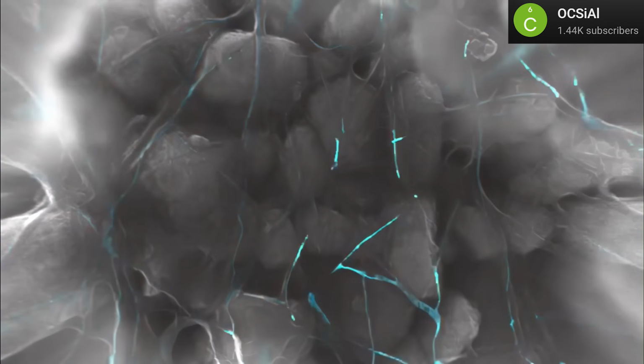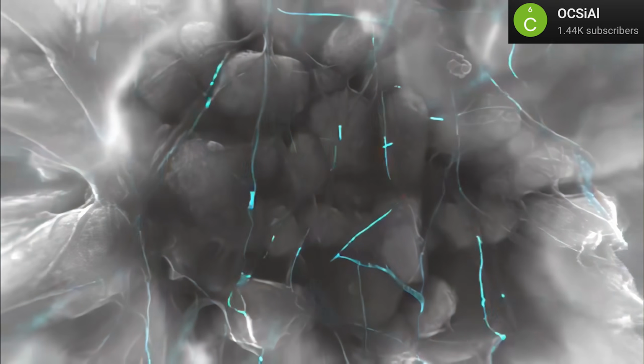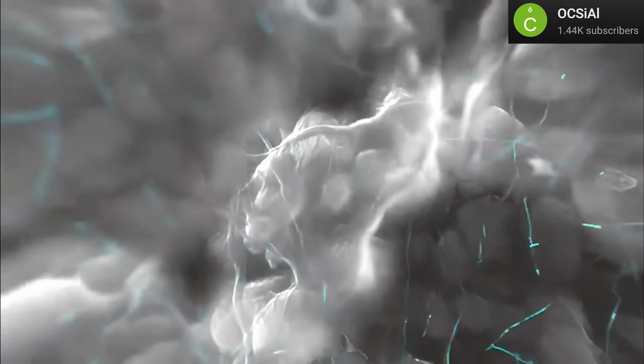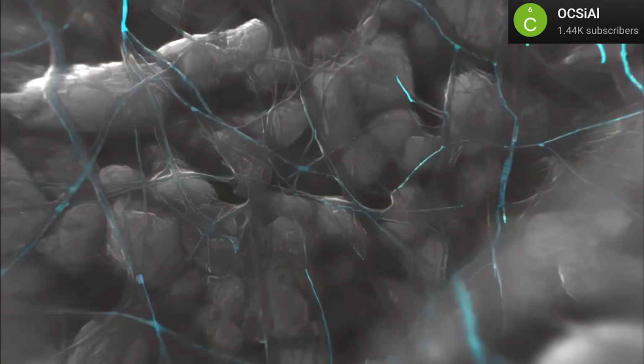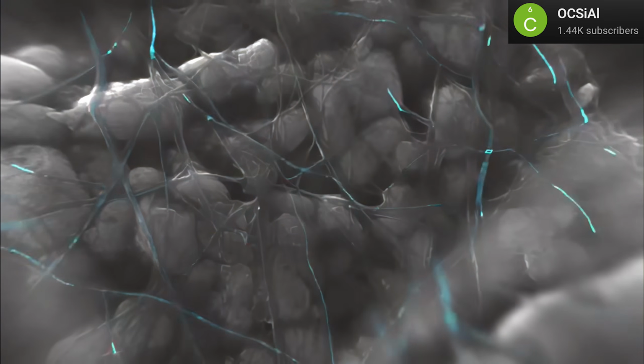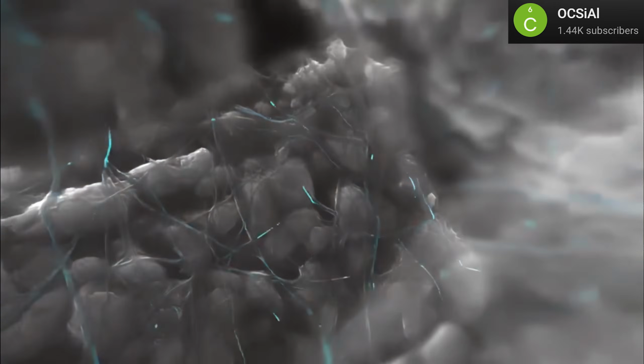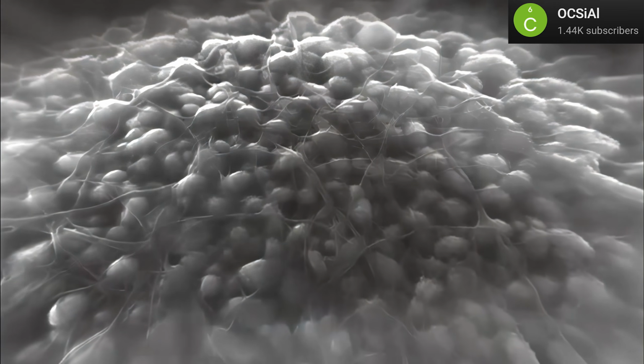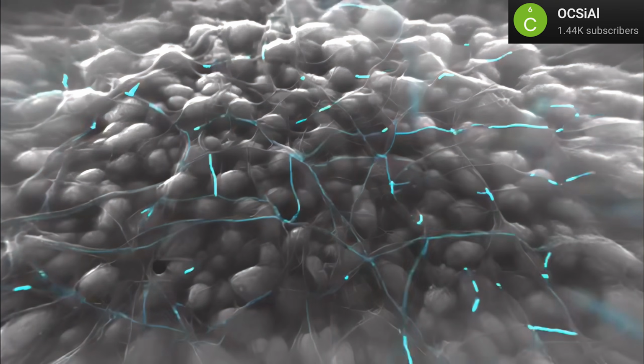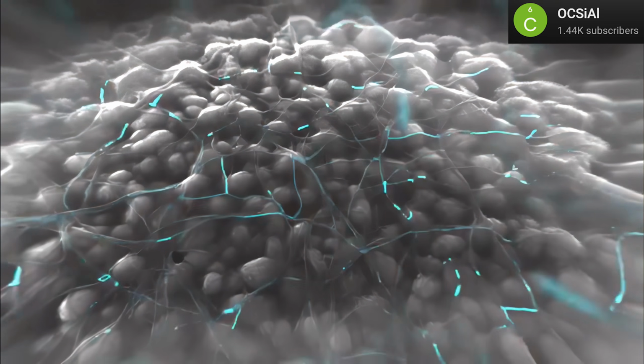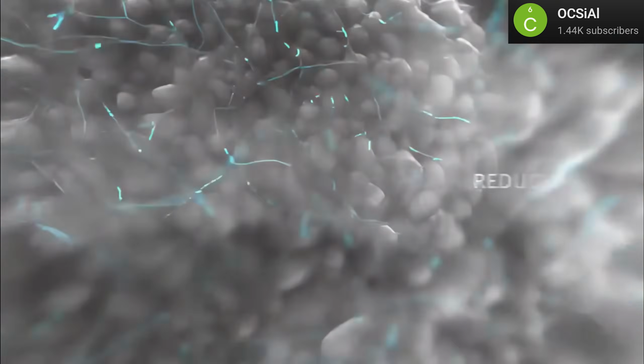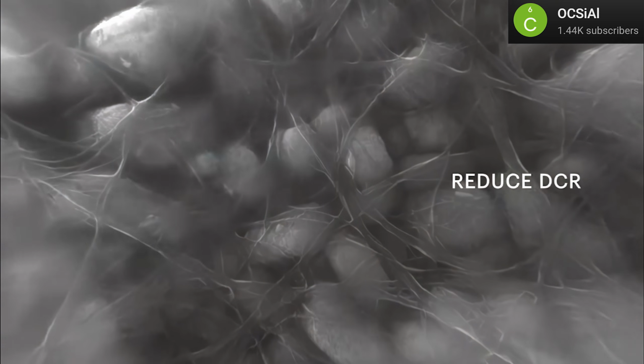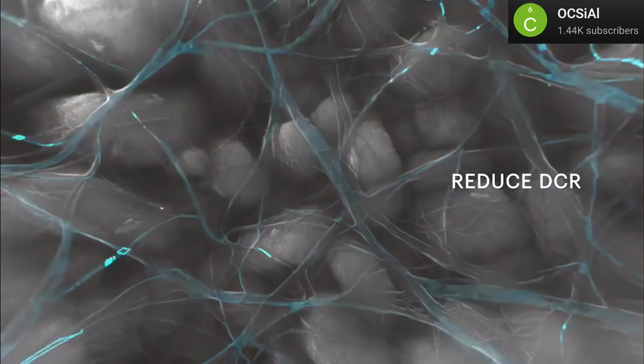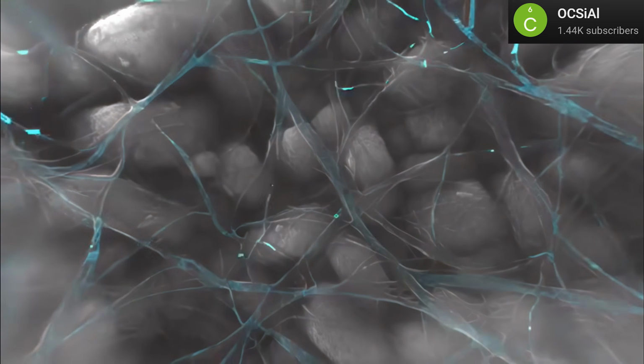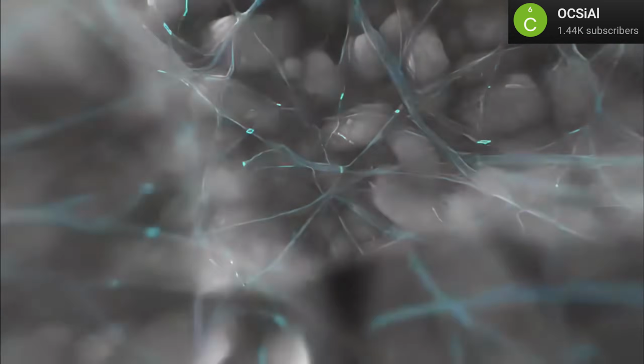As a side note, I imagine carbon nanotubes could also be used, and they might actually be cheaper. That's because although they cost 10 times more and have greater surface area than vapor-grown carbon fiber, they could be used at dosages of maybe 20 times less. However, I don't know if they'd entangle or bond with the PTFE as effectively as vapor-grown carbon fiber. Even if not, they would likely still improve high-voltage performance in wet or dry-coated cathodes by creating a more continuous electronic network with less reactive surface area than carbon particles.